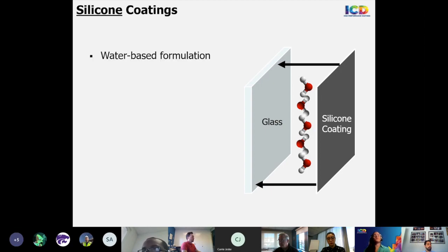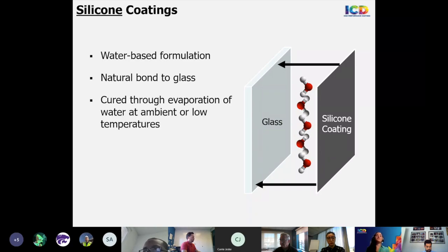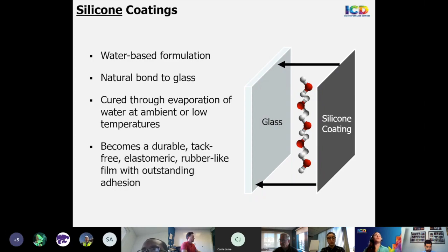So silicone is a water-based formulation, and that is one of the advantages of using silicone, that it is a sustainable, eco-friendly alternative to frit, which can be really helpful when architects are designing for LEED projects or other green rating systems. So silicone and glass actually have a very similar chemistry makeup. The primary constituent of both is sand. And so there's a very strong natural bond to one another, and the attraction is very high. Silicone is cured through the evaporation of water at ambient or very low temperatures, and after curing, it becomes a durable, tack-free, elastomeric, rubber-like film with outstanding adhesion.